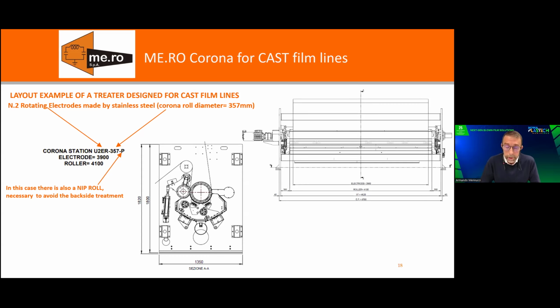So another feature that characterizes the treater for cast is the use, which is absolutely mandatory, of a pressure roll, nip roll, because the backside treatment is particularly critical on CPP lines, and you have to use a pressure roll with the proper characteristics. Otherwise, you risk to have backside treatment.